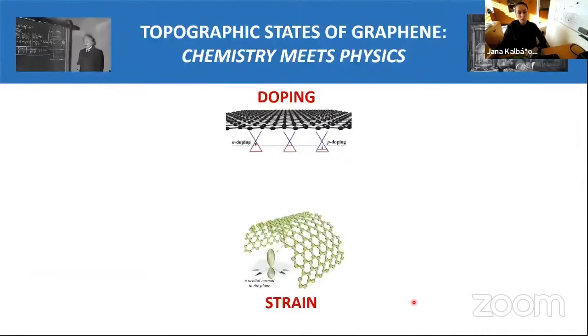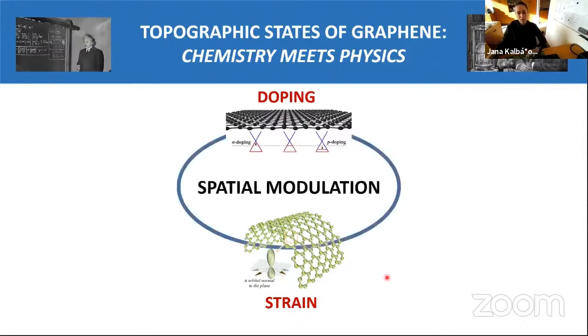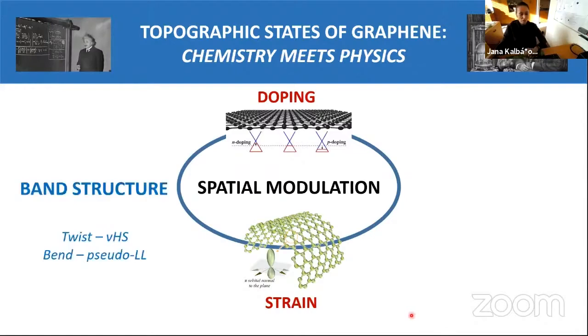So I will just jump to some kind of conclusions. Today it was really a hard task for me because I saw that I should probably choose completely different topics for discussion here. Nevertheless, I hope I have shown you that in principle, if we try to make some kind of topographic control over the graphene, we can reach some spatial modulation of the doping and the strain. And of course, it has many consequences. Regarding the band structure, this is quite clear. We can reach some Van Hove singularities, or we can even reach the Landau levels with our pseudomagnetic field for some specific shapes of the ruga.